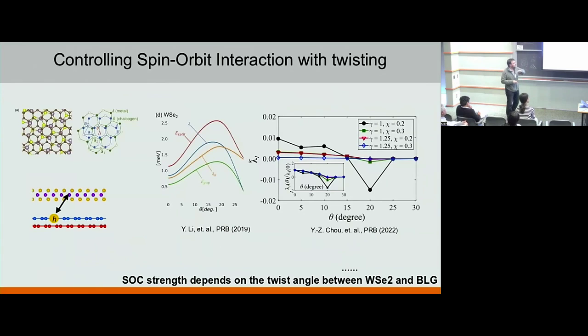Now we're going to do a similar exercise for several samples. I should mention that it was a known fact that if you tune the angle between your bilayer graphene and tungsten selenide, you can tune the strength of spin-orbit coupling. This was elaborated in several theoretical works, and it's easy to understand how this works. You just think about these holes virtually tunneling into tungsten selenide and back, and that gives you some effective spin-orbit coupling. You have to average over the sample, but these are highly non-commensurate crystals, so you can do this procedure.